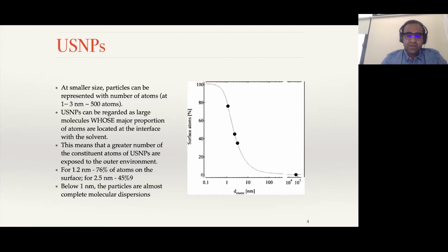Even though the particle is made up of gold, because the functional group present at the outer end is a thiol or an amine or a carboxylic acid, and I know that 76% of the atoms of this material are on the surface, even though my core material is made up of gold, it's not going to behave similarly. They're going to behave very, very differently. So that's the reason why people would like to reduce the size as much as possible, so that you can make these particles behave differently by changing their surface chemistry. That's the holy grail of why nanomaterials or nanoparticles are extensively being used. Okay.